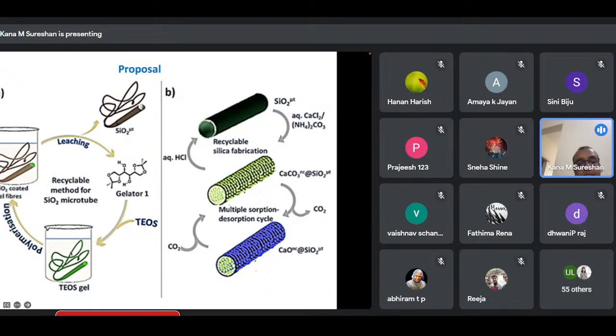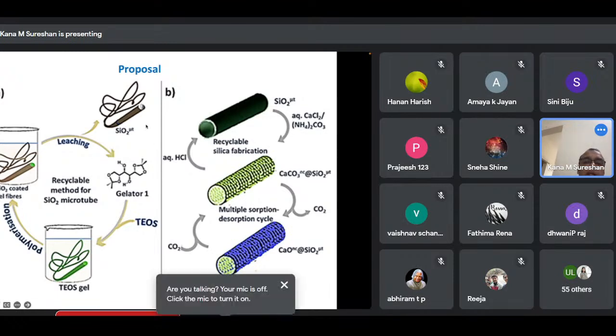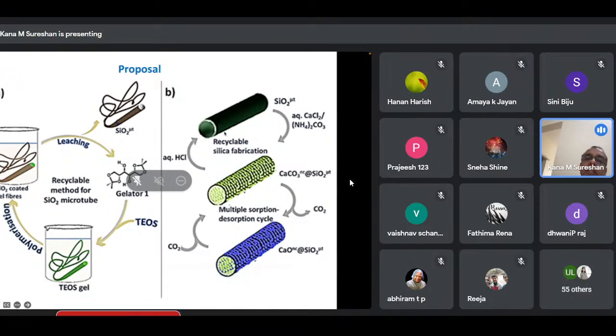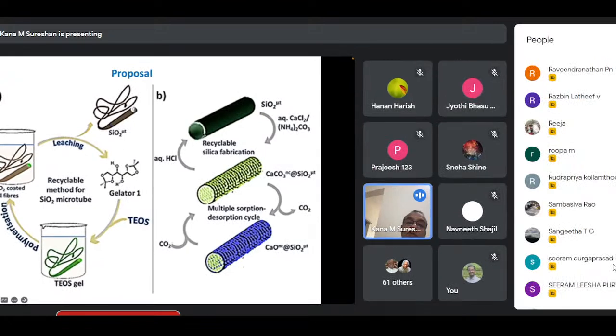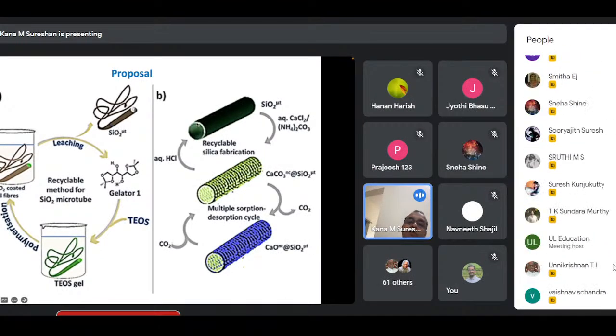So you make a gelator, and this is the schematic, actually. It will make a fibrous material. And then slowly you hydrolyze this and it will make silica around these gel fibers. Then you can remove the gelator from this tube, actually. What you get is this kind of cylindrical silica tube. And these are already micrometer sized tubes.